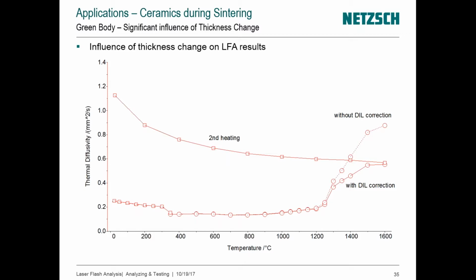So the first heating, you see it with and without correction, and now if we were to perform a second heating, in other words, the sample has been fully sintered, cooled down, and then we heat it again, then you will obtain what you see here with the square marks. And at the end, at the maximum temperature, in that case 1600 degrees Celsius, you see that the diffusivity value obtained at that temperature is fairly equal to what was obtained with the corrected data during the first heating. So simply to say that if you did not account for the change in thickness, you might have had the impression that the diffusivity obtained at higher temperature is slightly lower than what was obtained if during the first heating the contribution of the shrinkage was not accounted for. Very important again to be knowledgeable about that.